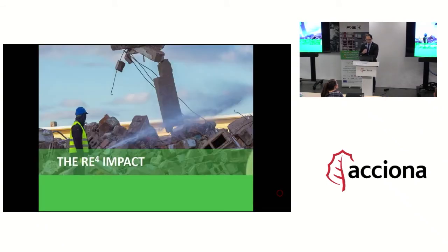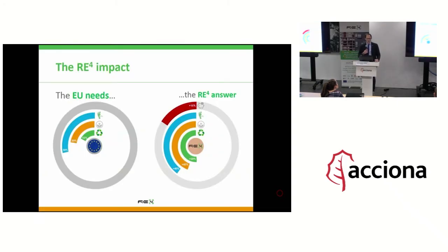Moving to conclusion, the RE4 impact. On the left graph, you can see where the EU needs to be in terms of CO2 reduction, embodied energy reduction, and the replacement of virgin material with recycled materials. And on the right, you can see the RE4 answer. We were able to provide more than 40% reduction of CO2 emission with respect to the request of a 30% reduction. We provided a reduction of embodied energy of more than 45% with respect to the request of 20%, and we were able to replace more than 50% with recycled materials with respect to the request of 50%.